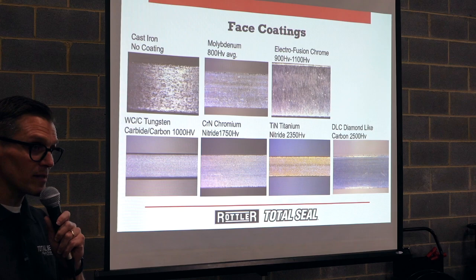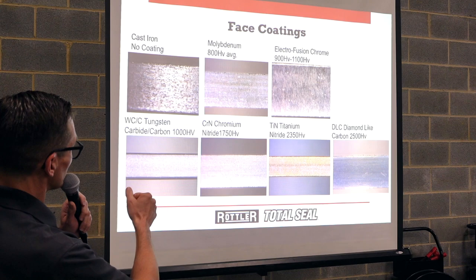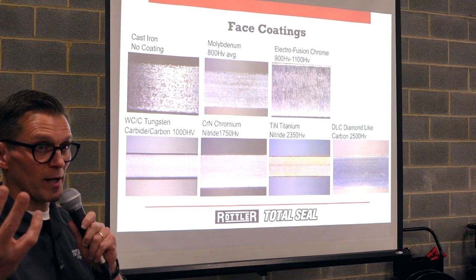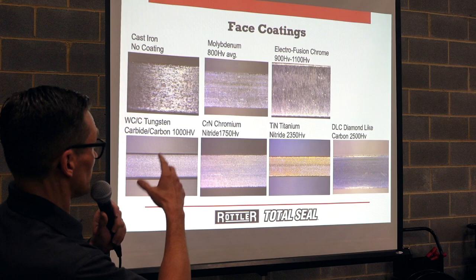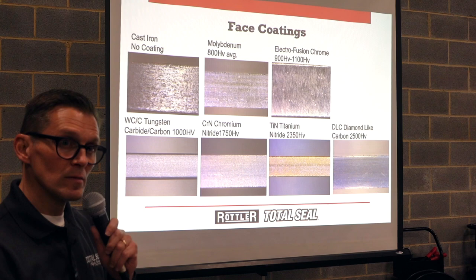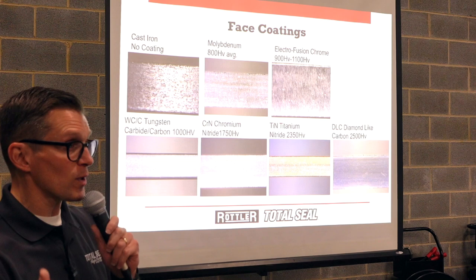But back in the day, they were just old cast iron rings. And then we got around to ductile iron and things, but then we got the moly ring. So the moly ring's been the staple for a long, long time. Even 20 years ago, it was the state-of-the-art in NASCAR. The great side of moly is it's soft. It has porosity, so it holds oil. That made it really easy and very forgiving on honing, because the moly would hold the oil.